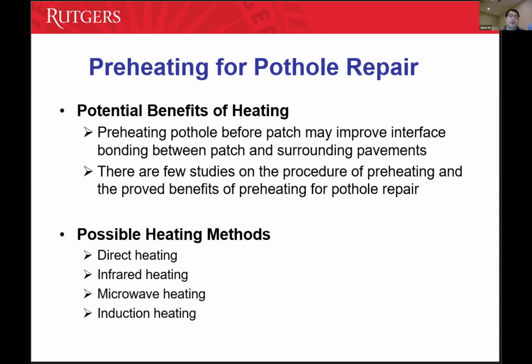But in this case, we're trying to see, can we preheat the pothole before the patch? We just do it for a few minutes, and hopefully we can improve the bonding between the patch and the surrounding pavement, because it becomes like a hot-to-hot interface instead of a hot-to-cold interface. It's also similar to longitudinal joint construction, to make the interface stronger.